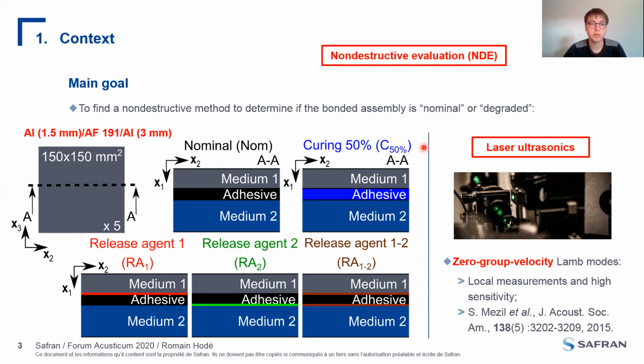So we have manufactured 5 different samples, which are all composed of 2 aluminum plates that are bonded together through a layer of an industrial adhesive. So we have here the nominal case, here the case where the curing time of the adhesive is about 50%. And we have 3 different cases with the addition of a layer of a release agent, at the first interface, the second interface, or both interfaces. And this layer of release agent is used here to degrade the practical adhesion between the aluminum and the adhesive. So the samples can't be discriminated with conventional NDT methods.